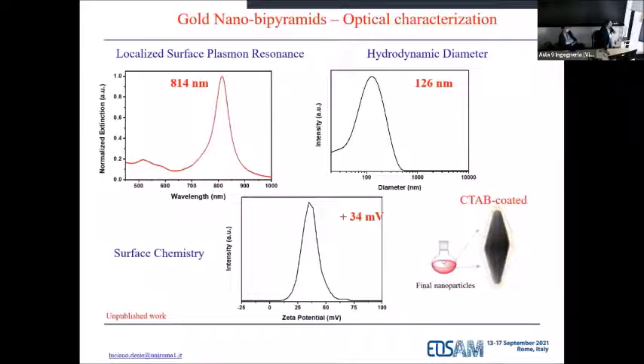First off, the absorption is exactly in the so-called biological window, so we are happy for that. Of course, the long diameter is more than 100 nanometers. It's something we are still trying to work with, but we are still in the so-called nano range. And lastly, of course, we have a positive surface chemistry.